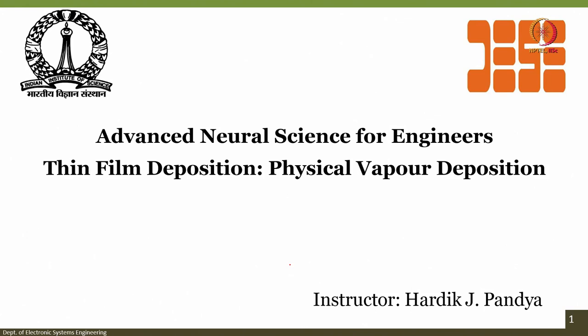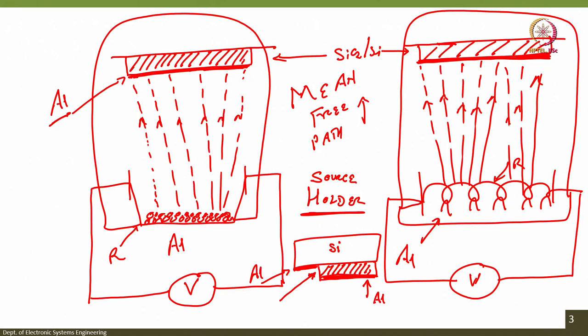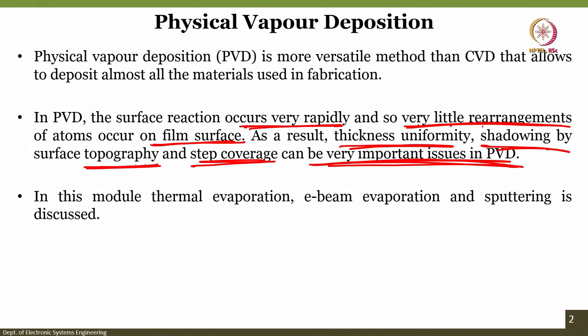Consider silicon with a silicon dioxide pattern. If you deposit aluminum, it deposits uniformly on the flat silicon and uniformly on top of the oxide, but at the step region the deposition will not be uniform. That region is called step coverage — covering the step uniformly is difficult in PVD, and this is a known limitation.